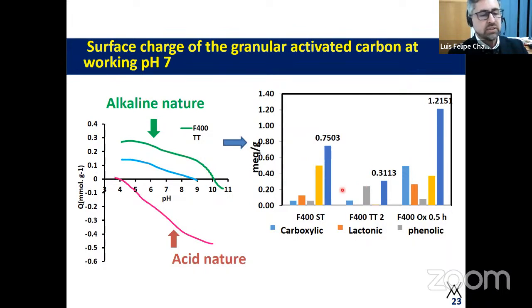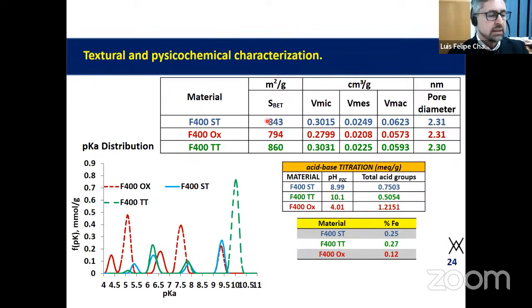And these profiles are consistent with the type of oxygenated surface groups, since the material with a higher acid character presented a higher number of carboxylic groups that are ionized at pH above 4.5. And these treatments did not significantly alter the texture of the materials, as you can see here, because they maintain a similar surface area. Instead, there was an important change in the surface chemistry, which is the effect that we wanted to study in the electroadsorption of arsenate.